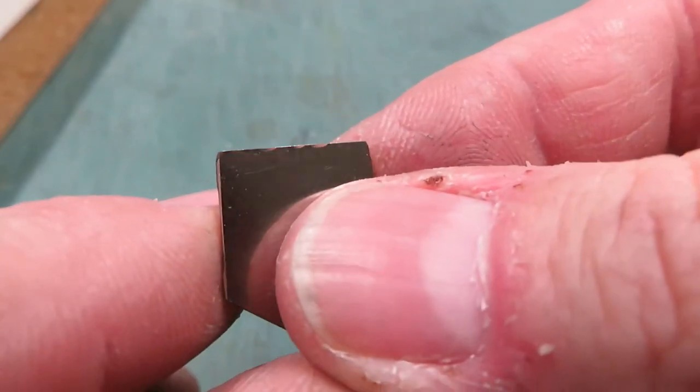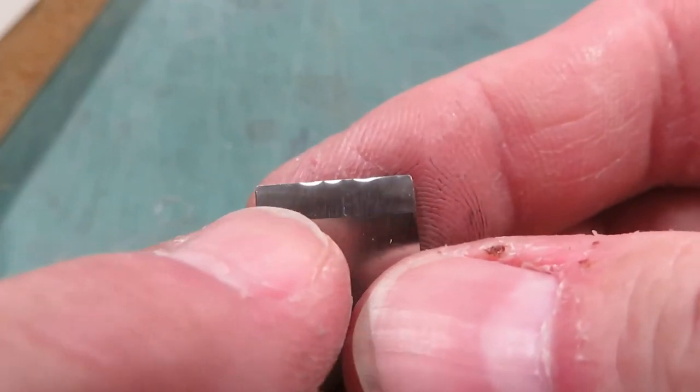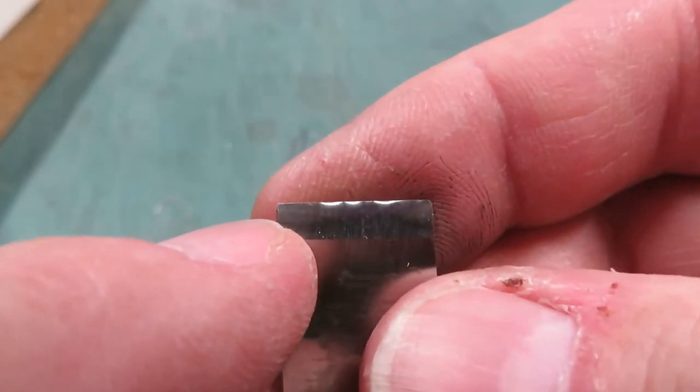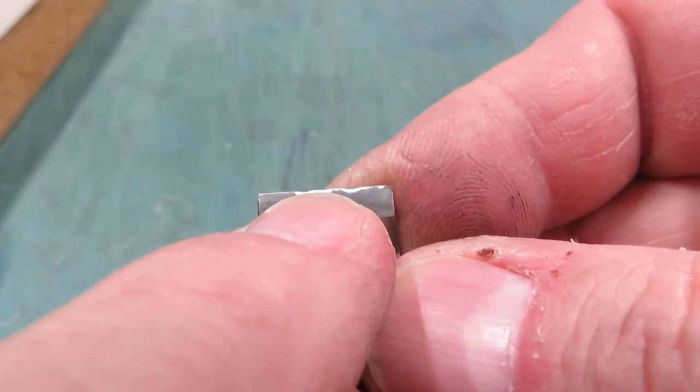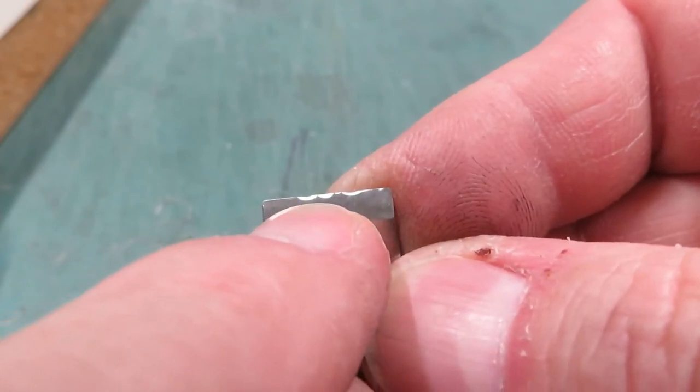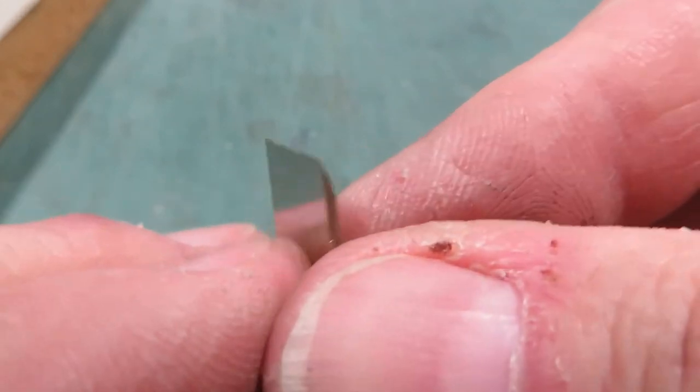I don't think the prior video showed very well what was happening, there was some focus issue. So I took the blade out of the vise and want to show you what that 20 degree single bevel edge looks like. After pushing on it with a wooden dowel, as you can see, it suffered some yield which is not acceptable in a broadhead, right. You want it to pass through the animal and be reusable. There's some really nice broadheads out there that are investments and you don't want them to be a single use, one time edge. What I mentioned earlier, the distance from the cutting edge down to where most damage occurs, where it's most susceptible, is about 20 thousandths from the edge. And that's what we're seeing here, the same thing. There's just not much metal there at 20 degrees.